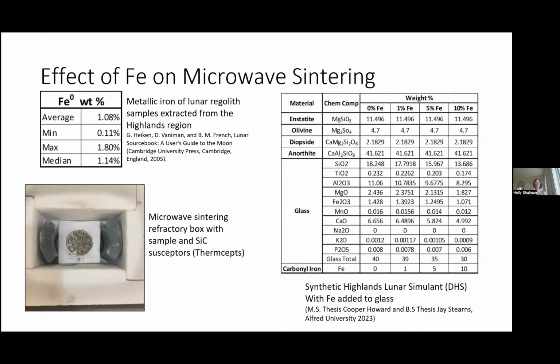I want to point out that your setup is going to influence everything about this process. So every time you change that setup, you've introduced a variable that is completely unknown. So for example, if you have a larger volume inside, you have radiation heat loss, certainly, and if you're running in argon, like these experiments, you have heat loss through other mechanisms too. So you really have to be very consistent and define your thermal package extremely well. The mass and volume of your susceptors will have an effect, and the mass and volume of your sample.